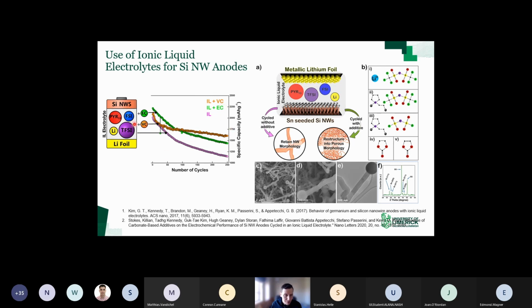Interesting point on this study was the majority of studies previously using ionic liquids for silicon had used the TFSI anion. We used a combination of the FSI and TFSI anion, and that was the best performing silicon nanowire electrode in an ionic liquid at the time of publication. Now, maybe that has changed now, but at least at the time of publication it was. The reason for that was the FSI actually gives the electrolyte a lower viscosity and hence a higher ionic conductivity. And that's the main reason. There are other reasons as well.